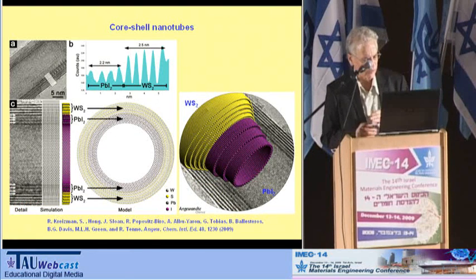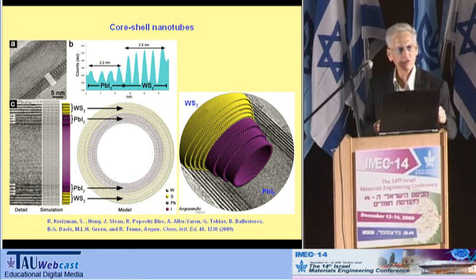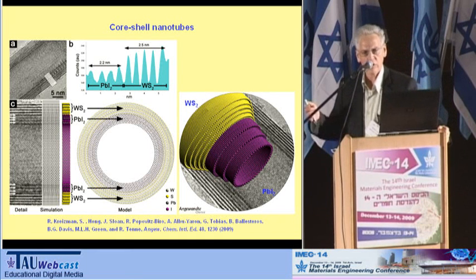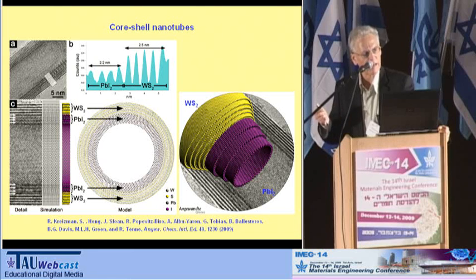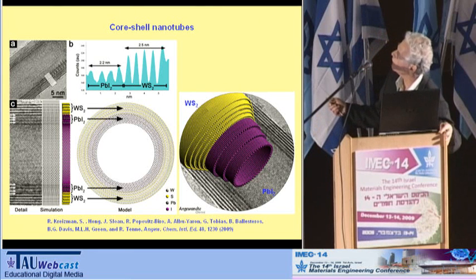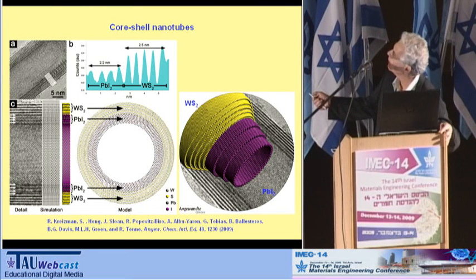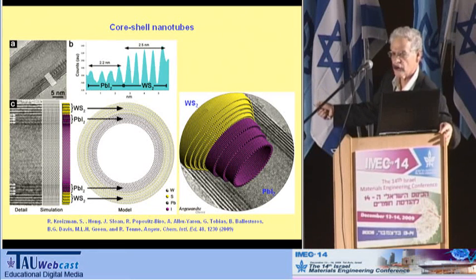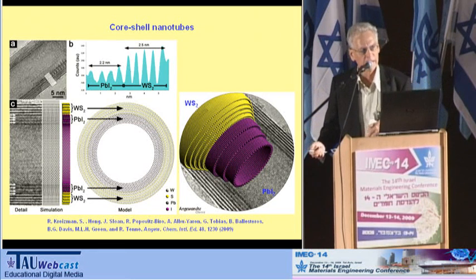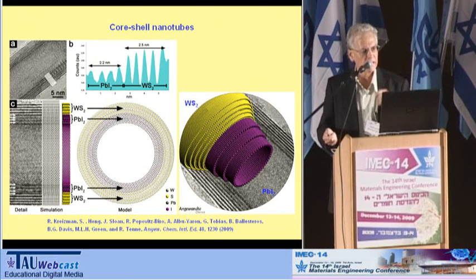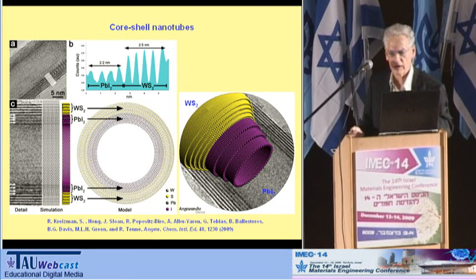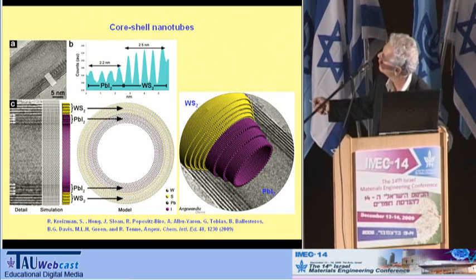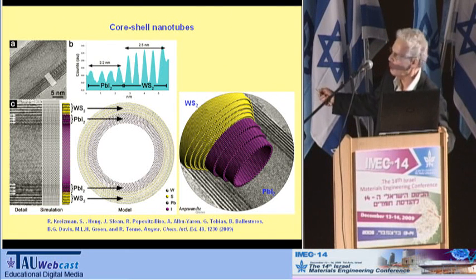More recently, we have published jointly with a student at Weizmann a new approach to synthesize new nanotubes using the tungsten disulfide nanotubes as template. So now we take the tungsten disulfide nanotubes and use a simple reaction with lead iodide. There are a few reactions that we can do. The simplest one is simply to melt the lead iodide in the presence of the nanotubes, and by capillary forces they go in and they solidify and they wet the surface and they form a nanotube within this nanotube.